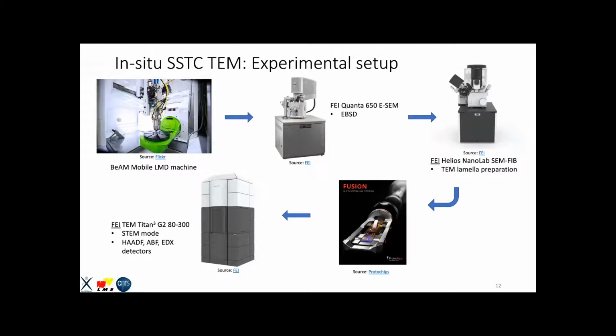into this Titan 3 TEM, which allows us to study, with all these detectors, the evolution of dislocations and precipitates, chemical heterogeneities. Now, the peculiarity of this fusion holder is that it allows us to go to temperatures up to 1200 degrees Celsius at a temperature rate maximum of 1 million Kelvin per second. So that's very nice. That's AM rates. And the disadvantage of this is that its tilt is literally 10 degrees, so we cannot really characterize dislocations. And our focus on this study was on chemical heterogeneity evolution. But we have figured out a way how to do the dislocation characterization as well.